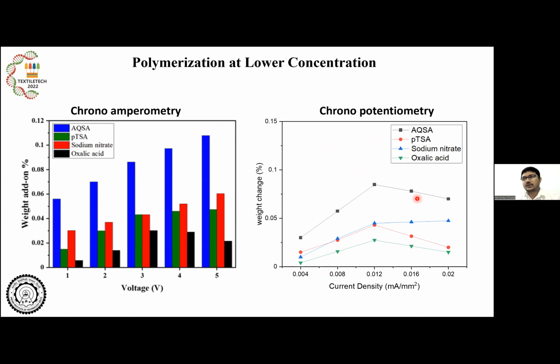So to counter this, lower concentrations of the solutions were used, and then again the properties were compared. It was observed that this weight add-on percentage increases every time as we increase the polymerization voltage. So in case of all the dopants, this current is increasing, and this weight add-on is increasing, and the polymer formed is higher, except in the case of oxalic acid.